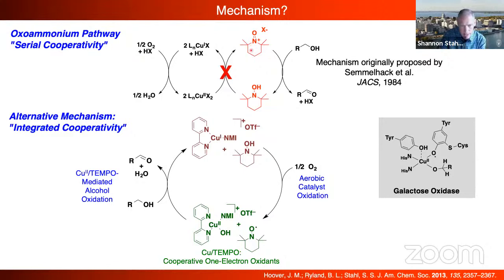This pathway is very much akin to what you see in galactose oxidase, where you have a copper-2 and an oxyl radical working in partnership to do alcohol oxidation in this sequence. So this is a 2-electron oxidation that uses 2 1-electron oxidants. So you're not actually going up to the oxoammonium. So this is not involved, but rather using TEMPO plus copper.